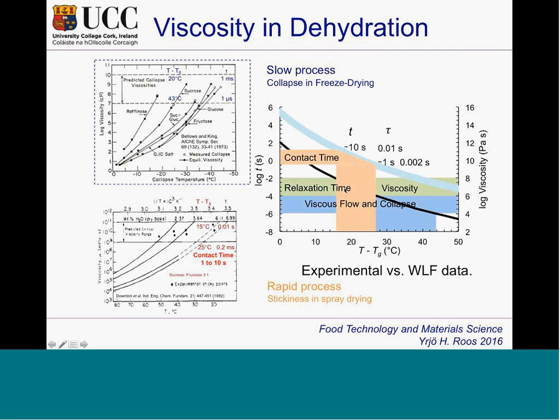And also we could say that the glass transition line is here, the black one, and the relaxation time goes from 100 seconds towards lower values rapidly above the glass transition. And there we could find a sort of critical zone about the glass transition where things start to happen in real time very rapidly.